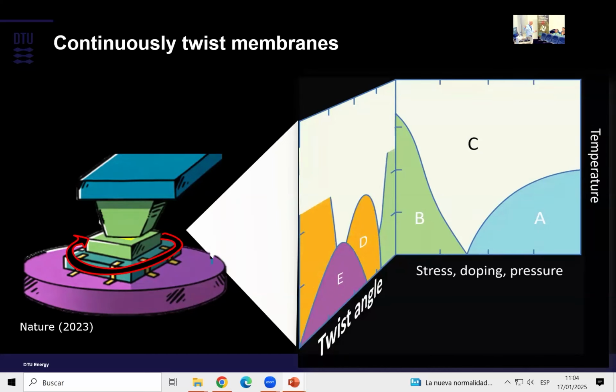And I must say that there is a challenge there, because we have seen, and we still see, but we are optimizing it, and many of the people working in the group, like Raesh, are also looking at it. There is always a residue of polymers. And even if we don't see it by X-ray, or by eye, we can see it by measurements. When we try to measure the electrical conductivity, we can see some response that does not correspond to a normal material.